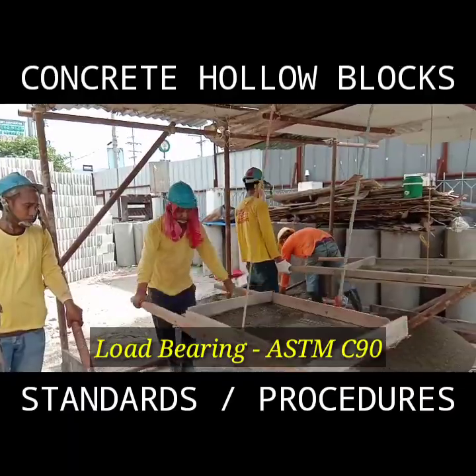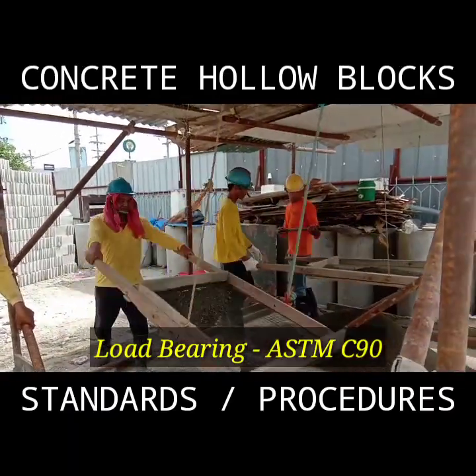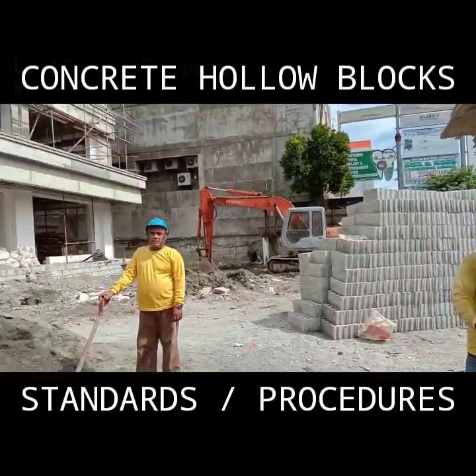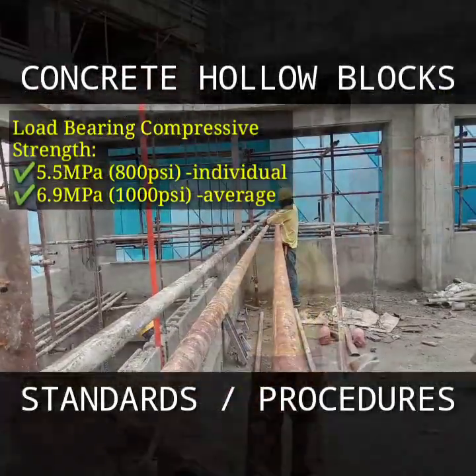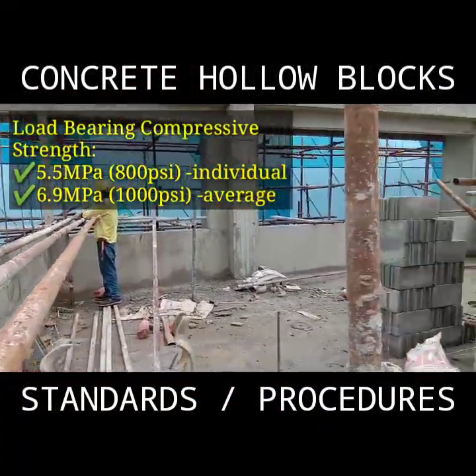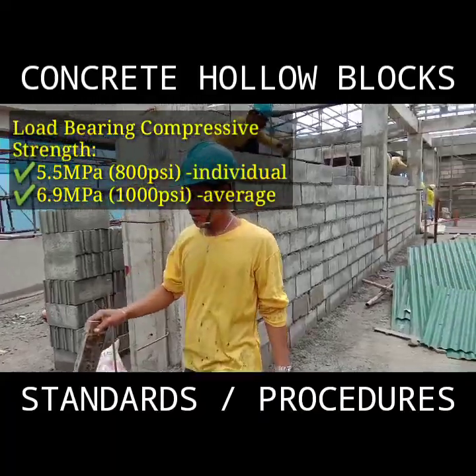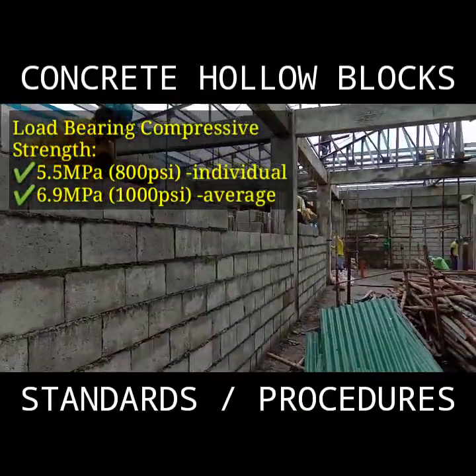ASTM C90. And each block, when tested for compressive strength, must reach 5.5 MPa or 800 psi, and 6.9 MPa or 1000 psi on its average compressive strength.